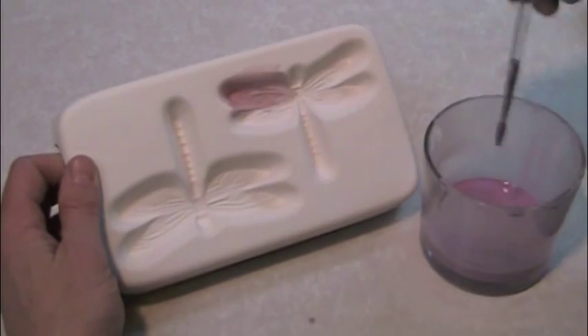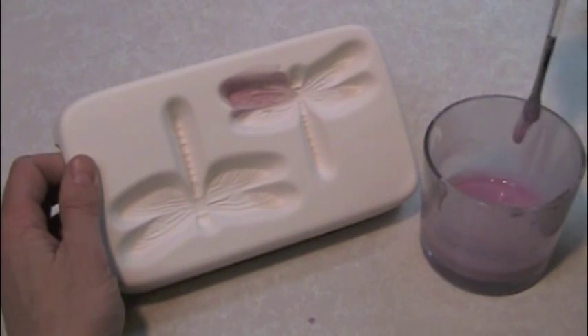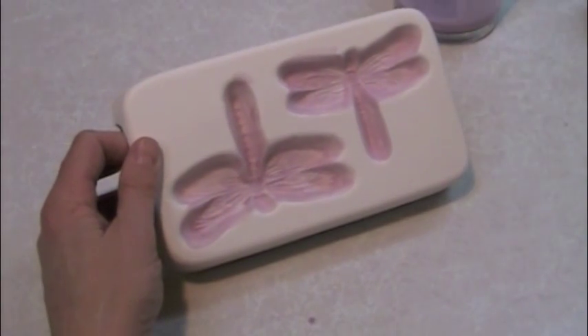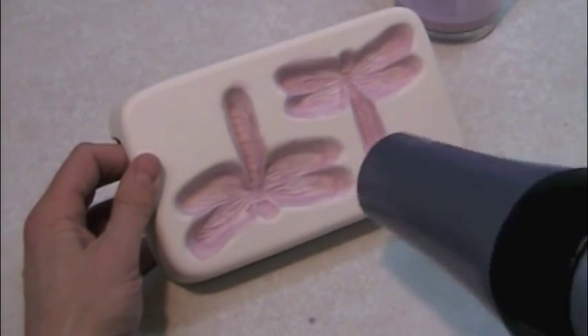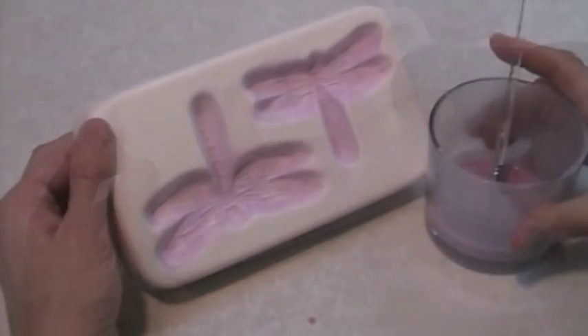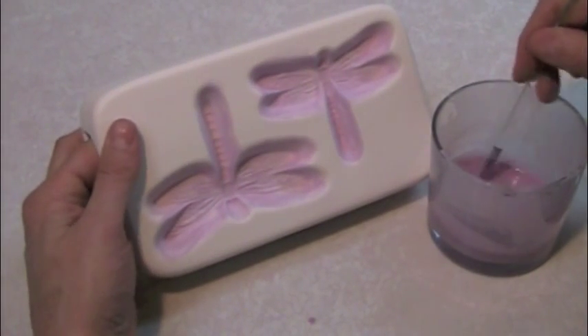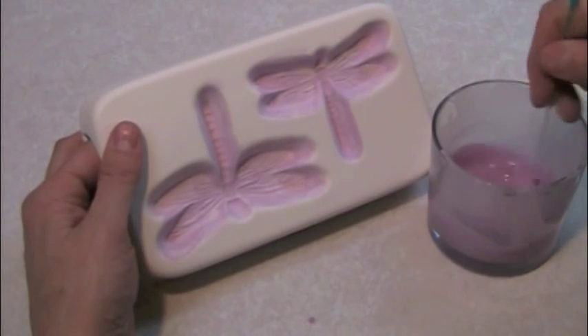Primo settles very quickly — make sure to stir it every time the brush is dipped. After the first coat is applied, use an ordinary hair dryer to completely dry the surface. Apply two to three more coats, drying each coat completely before applying the next.